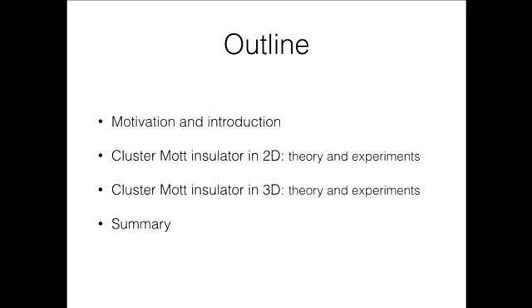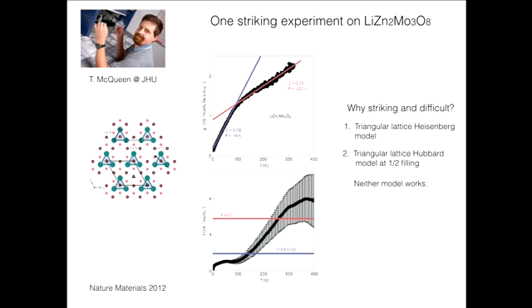So I'm going to the two-dimensional cluster Mott insulator. I was talking about a striking experiment. What is the striking experiment? This is the striking experiment done by Tyrel McQueen at Johns Hopkins University in this material, lithium zinc molybdenum oxide. In this material, it's called a triangle lattice of triangle clusters. These green atoms are molybdenum atoms. They form a triangle cluster.